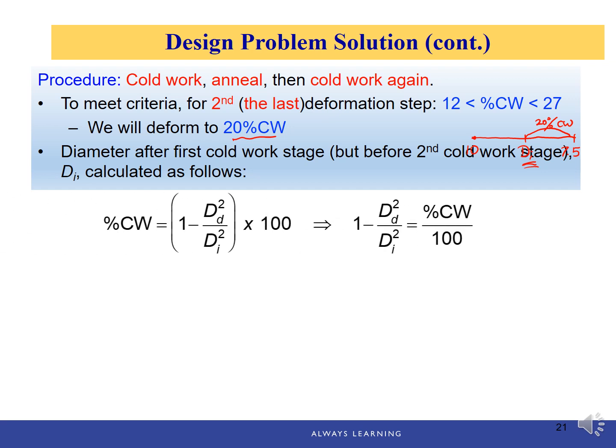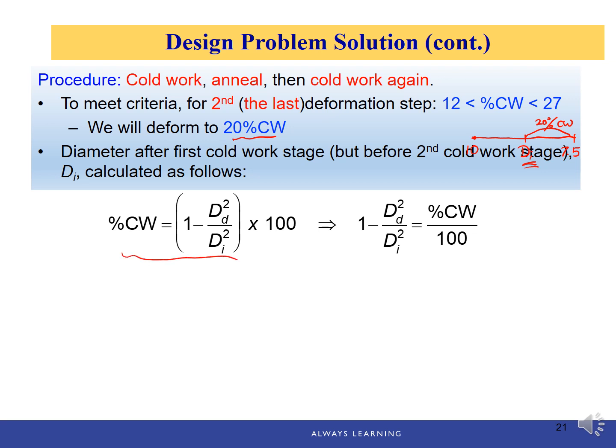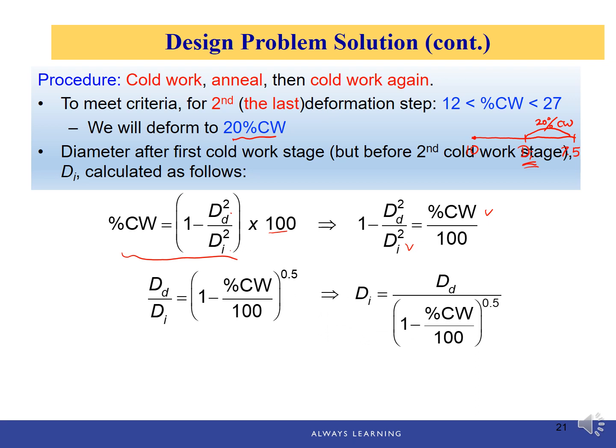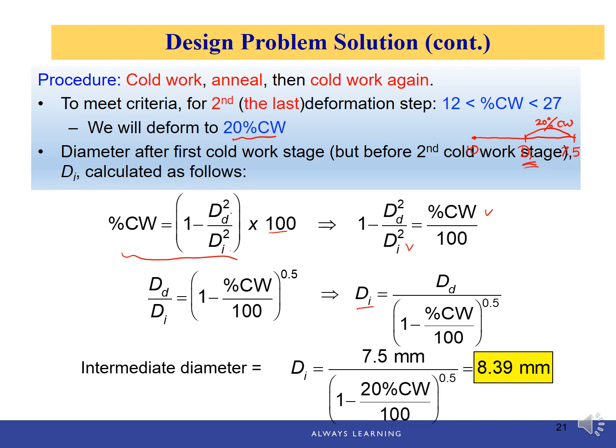And again, we're going to use the percentage cold work equation, the simplified version. We just reduced the percentage of cold work equation from the use of cross-sectional areas to the diameters: (D final over D initial) squared times 100%. Rearrange it. We know the D final is 7.5. We know the percentage of cold work should be 20. And from that equation, we can calculate the diameter after the first cold work stage, or the intermediate diameter, which is 8.39 millimeter. So the first drawing reduces the diameter from 10 to 8.39, and then we're going to anneal.